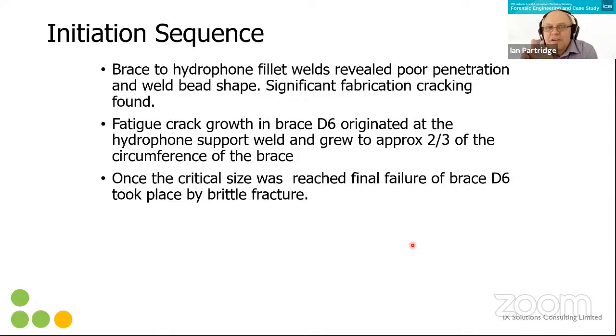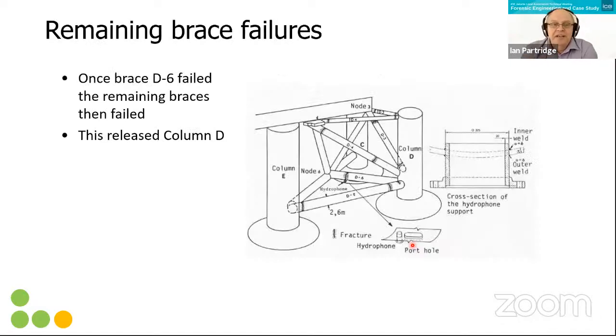What happened was the hydrophone fillet weld on the brace had some poor penetration and weld shape and some fabrication cracking. Fatigue crack growth occurred in D6. It grew till it was 2/3 around the circumference of the brace. And once at a critical size, it cracked and failure of the brace occurred. This then cascaded, and it's shown a lot easier here.